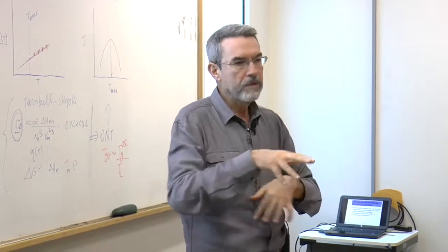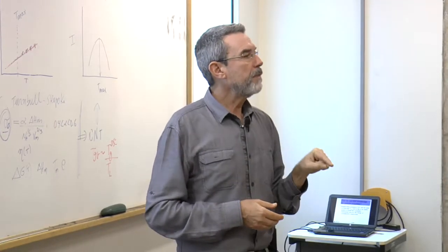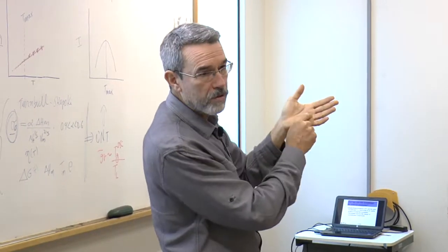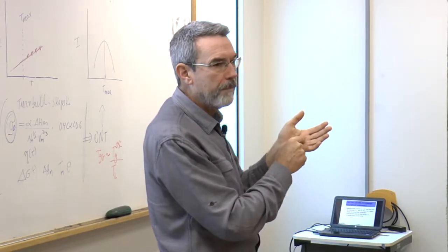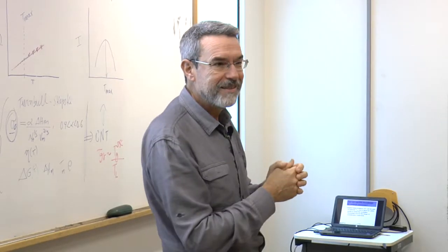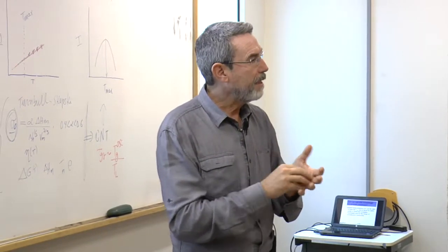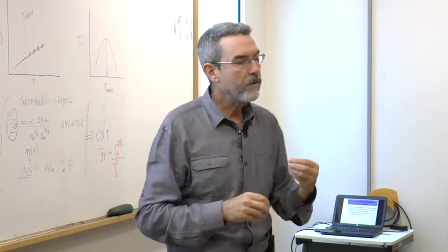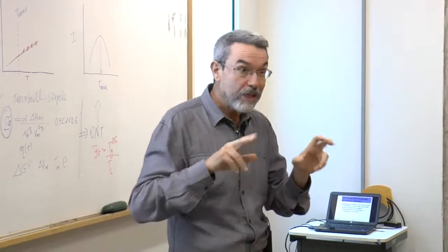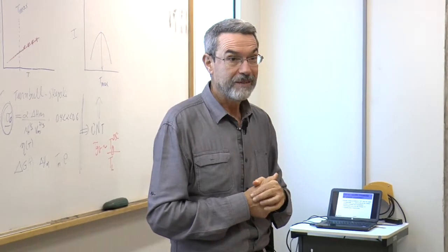You have to digest, and they dissolve, and they go to the blood, and so on, and act on some kind of diseases. Now, some of these materials lose their validity. You see, when you buy a medicine, there's the validity, half a year, 1 year, or so on. You know why? Several of them in the atmosphere absorb a little bit of water and CO2, and they crystallize. When they crystallize, they are no longer soluble, and they lose their validity. So many people in the medical area work not only on the chemical principles of their medicine, but they add a lot of extra substances to make a very stable vitreous material. This is very important. Okay?